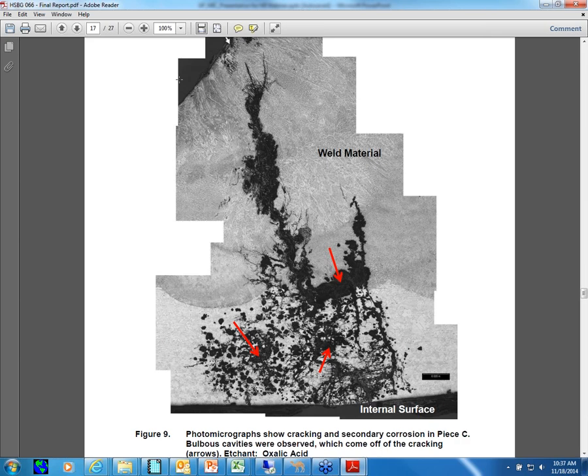That was one of the stumbling blocks, I guess, for us in the early days as we were learning about microbially influenced corrosion and how it worked. Although it looked a lot like chloride stress corrosion cracking, the root cause would actually be the microbes growing on the surface.